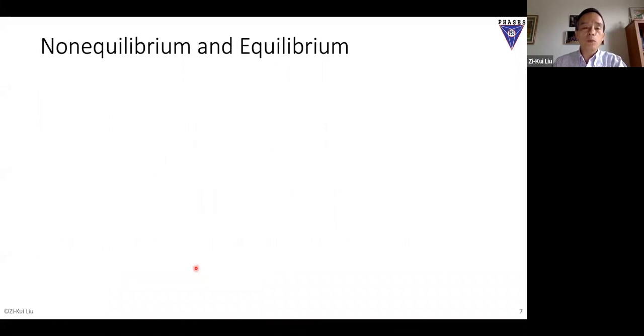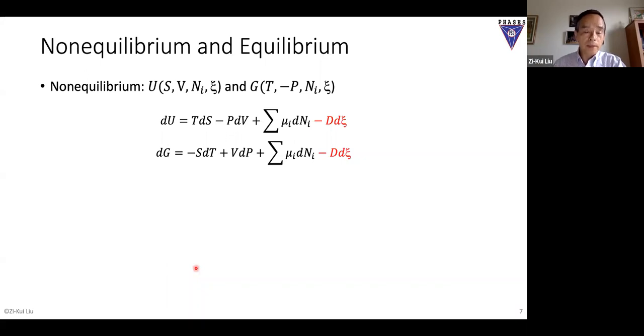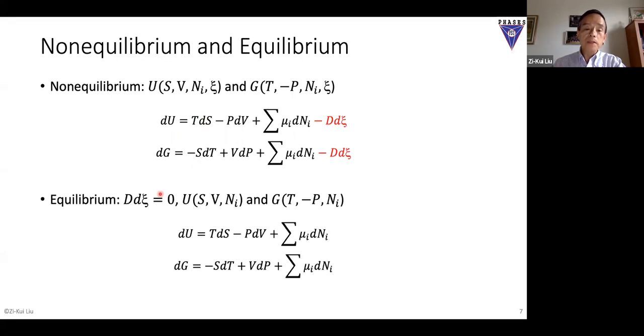Okay, now equilibrium thermodynamics. So what's the difference then? Well, this is non-equilibrium thermodynamics. We have xi here. We use one internal process, but it could be multiple internal processes, say xi j. So for non-equilibrium thermodynamics, you must have this term in there. That means the energy is a function of internal state. And the same for the dU, that's internal energy. Then for the dG, you just switch the contributor variables. And for equilibrium thermodynamics, that means that d xi equals 0. And now you see the xi drops from the function here because it becomes a dependent variable. That's why as soon as you use these two equations, it's equilibrium thermodynamics.